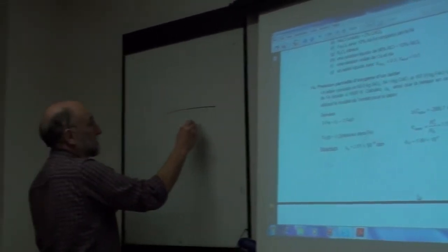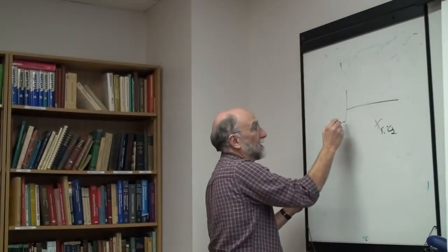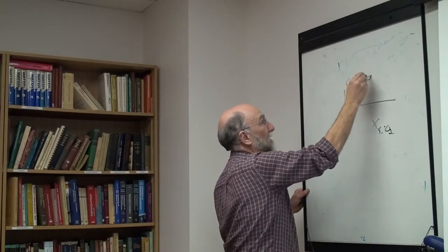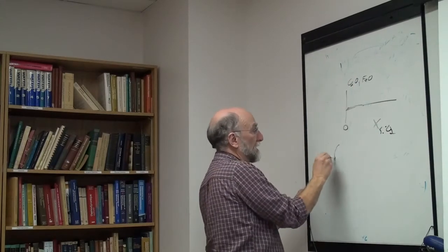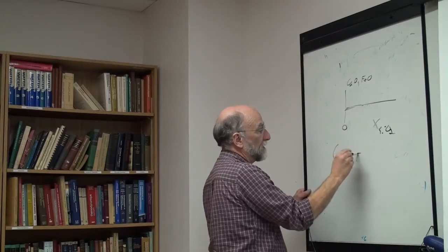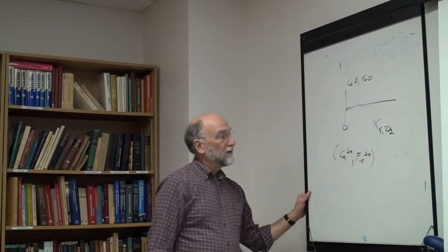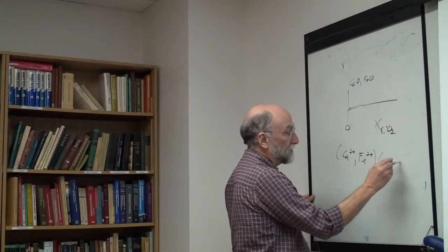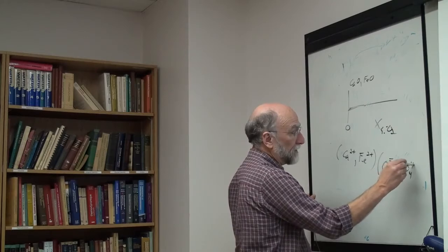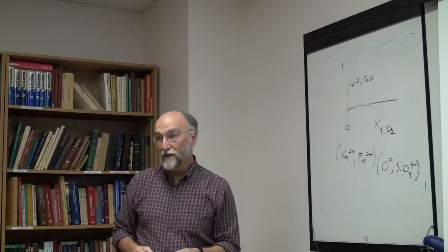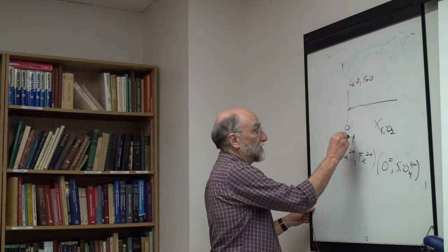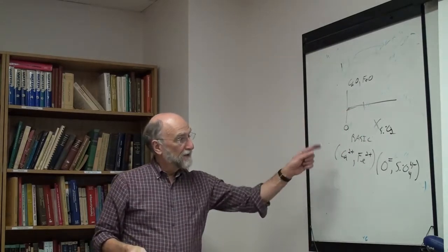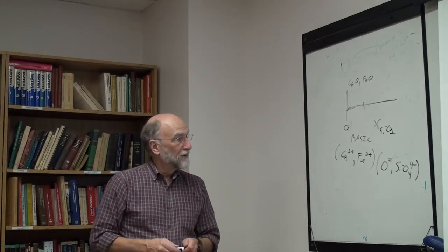If you've got over here, this is your mole fraction of silica, and zero when you're in this region here, where you've got a lot of calcium oxide and iron oxide, very little silica, then you have calcium ions and iron ions. You have the metal ions on the cation sites, and on the anion sites, you have oxygen ions and orthosilicate ions. And this is your basic slag region, holding up to about 33% silica. This is the approximate model that you can use.